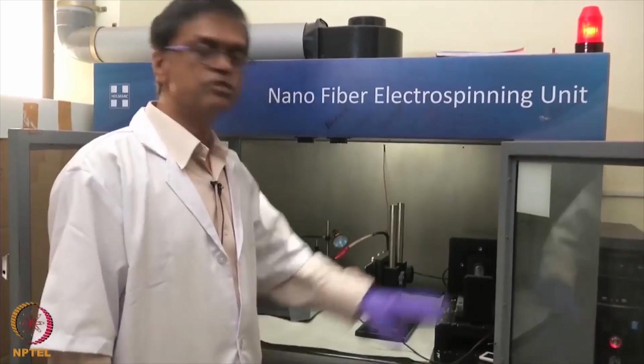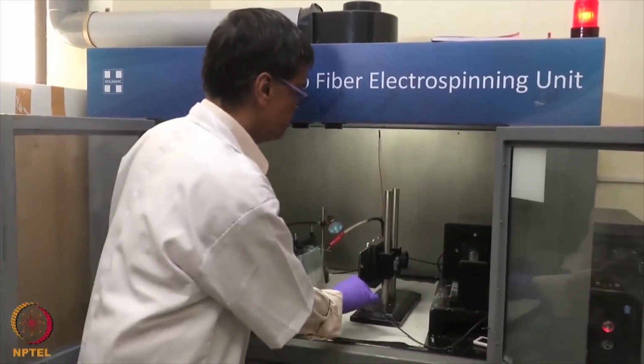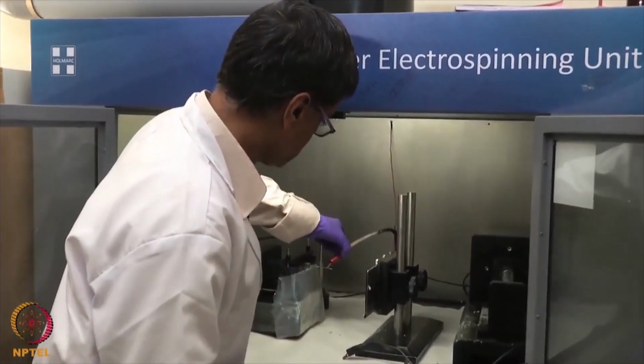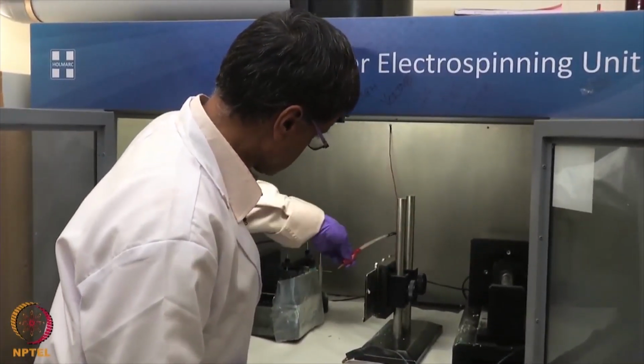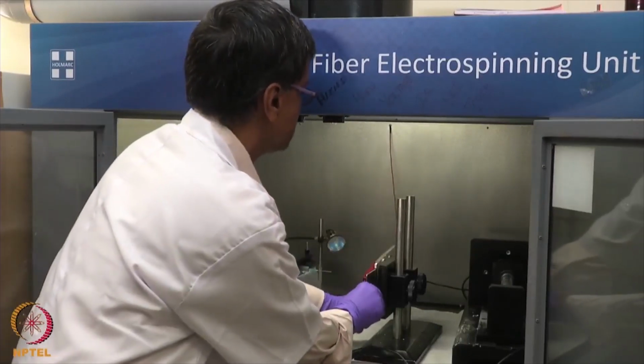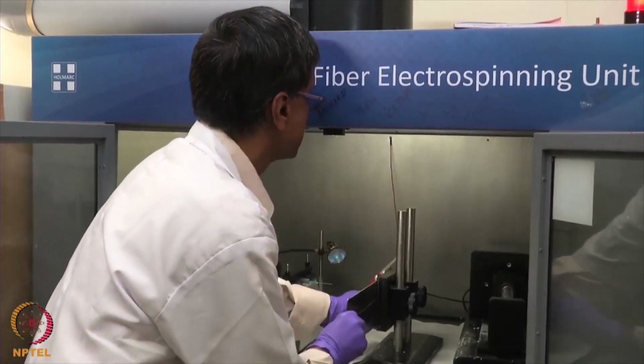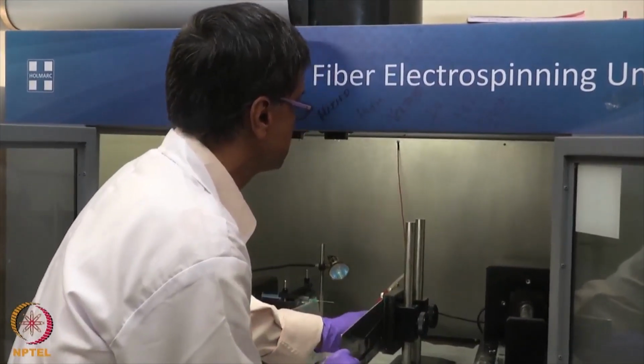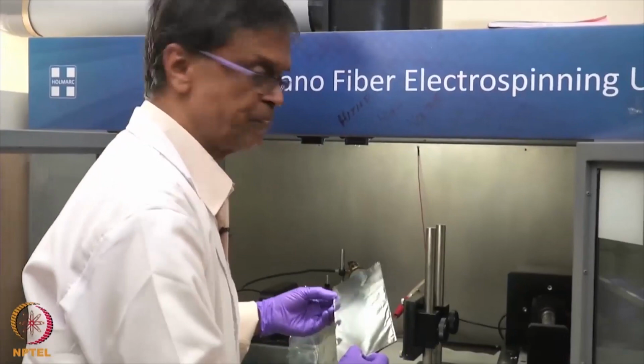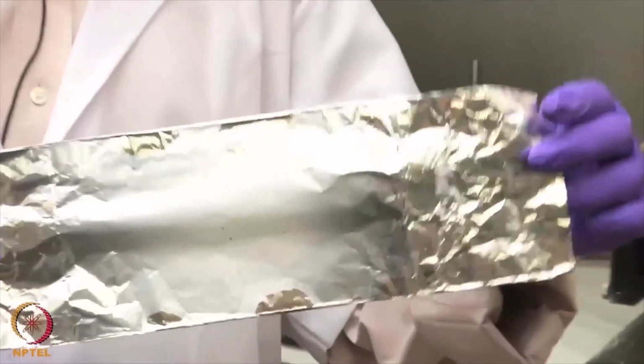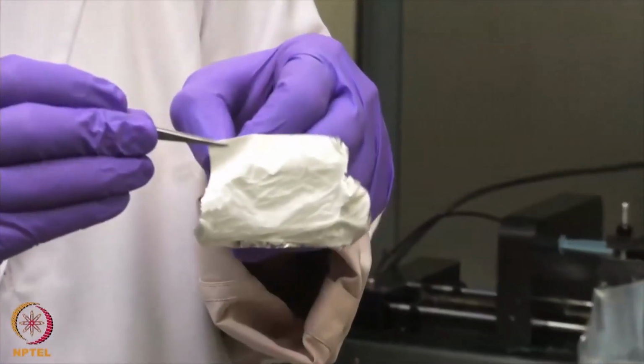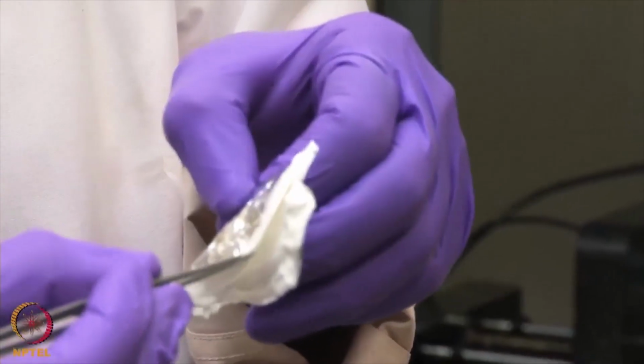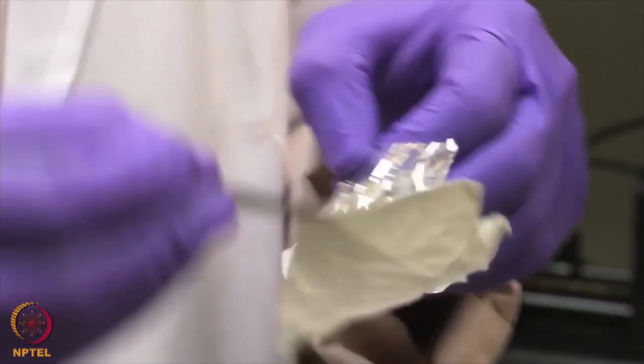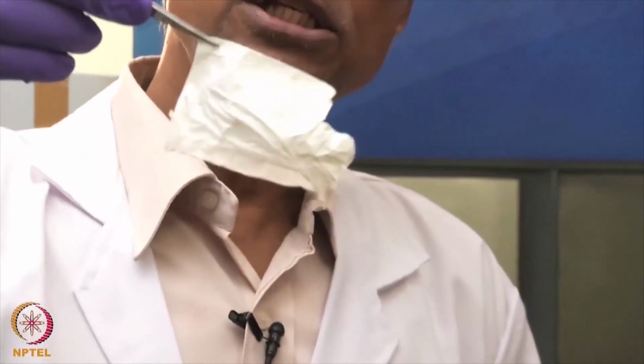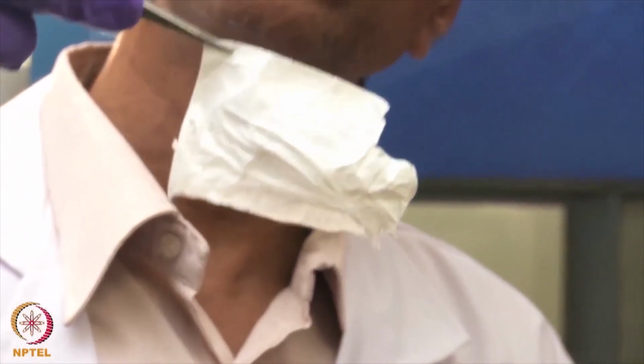Once we have collected enough fibers, we switch off this machine, we remove the voltage plates, and then we remove the collector slowly, and we can see the deposit of the polymer. We can see the deposit of the polymer nanofibers on this aluminum foil. We can nicely peel it off, as you can see here, from the aluminum foil, and this is a nanofiber of polyvinyl alcohol.